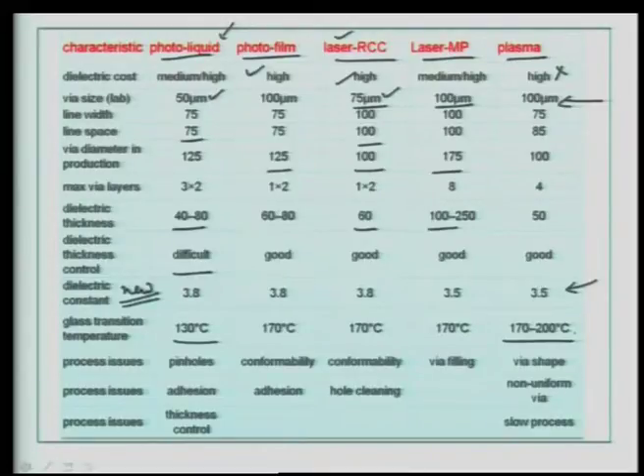Process issues are working in a clean room, therefore, things like a pinhole, debris sitting on the liquid photopolymer with no protection and so on can be very destructive in terms of the yield part of it, because of lot of rejects. Because the size of the via itself we are talking about 75 to 100 micron. Therefore, your pinholes represent a significant defect. And you have to look at the conformability of your drilling process, especially the laser, with the dielectric material. And also, if you are talking about the process issues in terms of the PWB processing, because it goes through the various chemicals, and then the substrate compatibility.